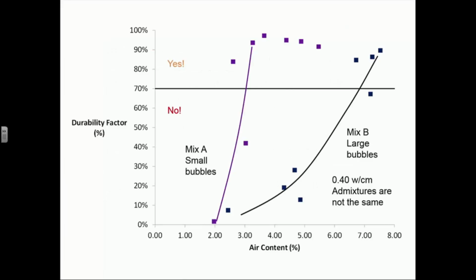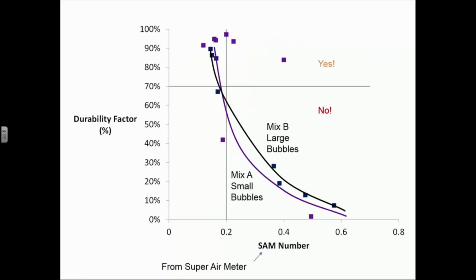So this is the graph I showed you earlier. This is the graph where we had air content at the bottom. We have durability factor, freeze-thaw performance, and we have these two data sets. And it's really hard by just using air volume to tell these two apart. For example, at 5% air, I cannot tell whether I'm going to have a freeze-thaw durable or non-freeze-thaw durable concrete mixture. But if I use the SAM number instead, okay, this is the number from the super air meter, you can. All the data is leveled. All the data is on top of one another. You can determine the difference between a good air void quality or good freeze-thaw performance versus bad freeze-thaw performance by using the SAM number. Okay?